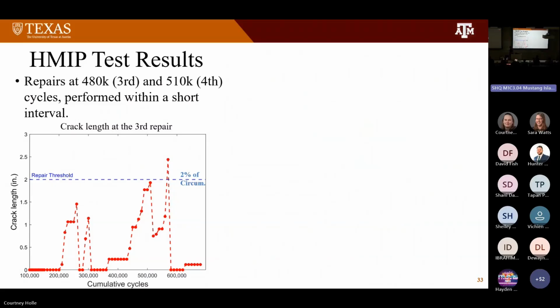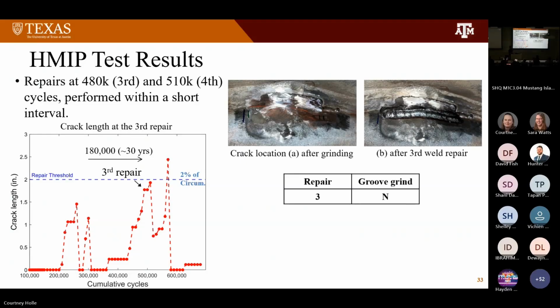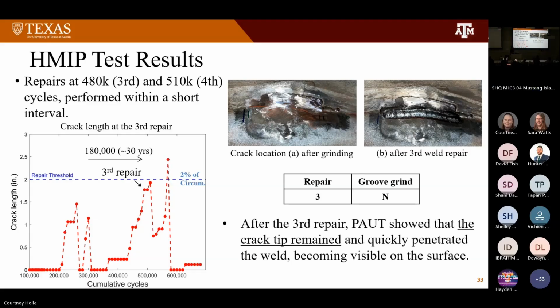The third and fourth repairs were performed within a short interval. The main goal of the third repair was to see if a relatively shallow crack, with a depth of 0.05 or 0.1 inches, could be repaired by direct welding without grinding. The result wasn't ideal. The crack was merely covered and soon penetrated through the cover passes and reappeared on the surface.